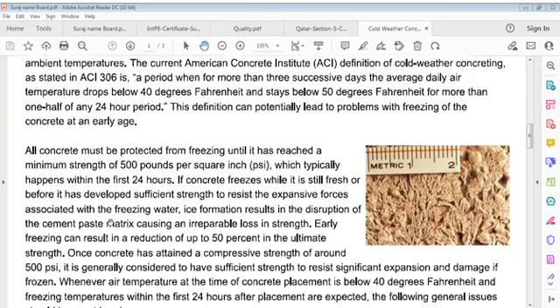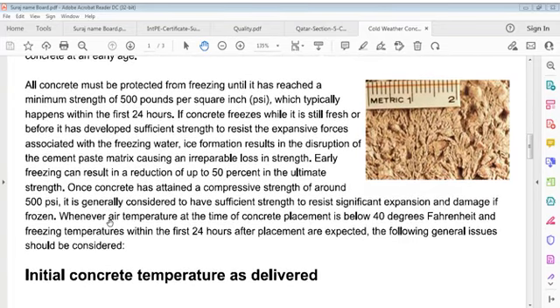All concrete must be protected from freezing until it has reached a minimum required strength, which typically happens within the first 24 hours. If concrete freezes while it is still fresh or before it has developed sufficient strength to resist expansive forces associated with freezing water, ice formation results in disruption of the cement-based matrix, causing an irreparable loss in strength. Early freezing can result in a reduction of up to 50% in ultimate strength. Once concrete has attained a compressive strength of around 500 psi, it is generally considered to have sufficient strength to resist significant expansion and damage if frozen.